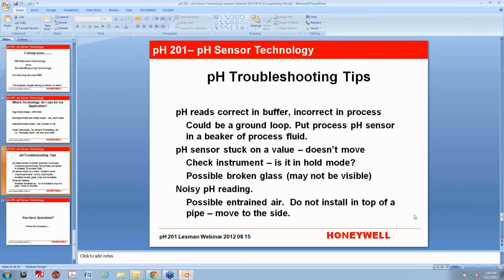The first one: I tried to list three things that I see happen a lot. I see a lot of ground loops out there. You may have a mixer or something in your tank, and it may have a faulty ground that's been in there for a long time, and that can cause voltage to be in the process that doesn't belong. The pH sensor, because it's generating a millivolt signal, expects to go to instrument ground when the signal comes through. If you have voltage in the process that doesn't belong, if your process is not at earth ground, that forces extra current to go through the sensor, and it gives you a wrong reading.